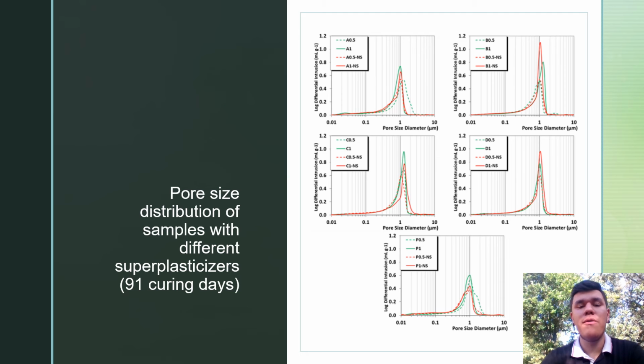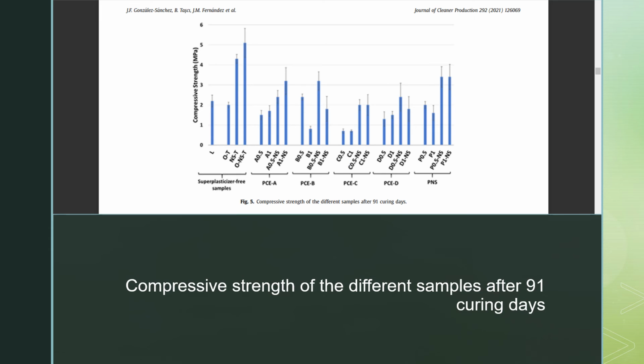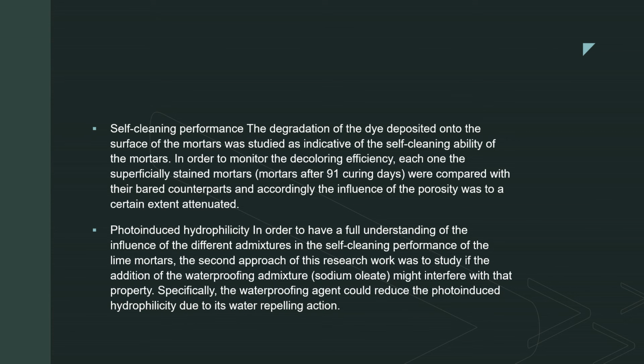This is a graph of the pore size distribution of samples with different superplasticizers after 91 curing days. This is a graph of compressive strength of the different samples after 91 curing days. Self-cleaning performance, degradation of the dye deposited onto the surface of the mortars, was studied as indicative of the self-cleaning ability of the mortars.